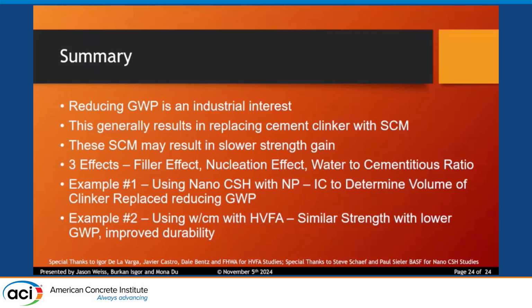So in summary, reducing global warming potential is a real industrial need, and we will see more and more people pushing toward this, all right, in the coming years, and they need to do this soon. So there are many promising technologies out on the horizon, but there's things that we can be doing soon. Generally, we're replacing a lot of the cement clinker right now with SCMs. The SCMs can result in slower strength development. 3 ways that we can try to counteract that: quantifying the filler effect, using nucleating agents, nanomaterials, and altering our water to cement ratio to get to a similar gel to space ratio at your critical time. We showed 2 examples, one with the nanoseeds and one with high volume fly ashes, where this was demonstrated and shown that this could be done at scale and is actually being done in commercial plants.